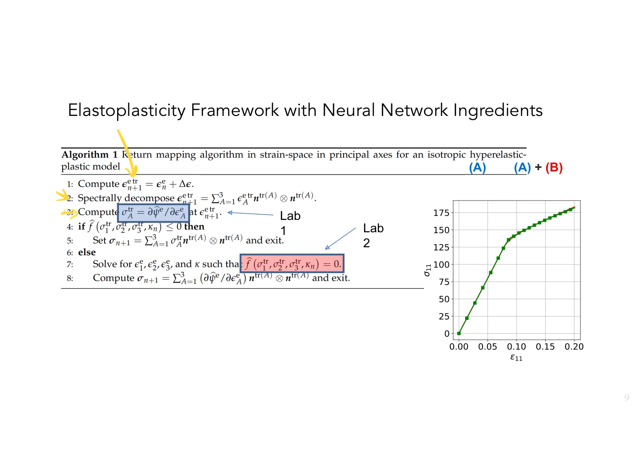We update the stress. We check whether the material is yielding, and if it's elastic, then the trial stress and the actual stress are equal to each other. If it's not, then this is the major part of the plasticity.